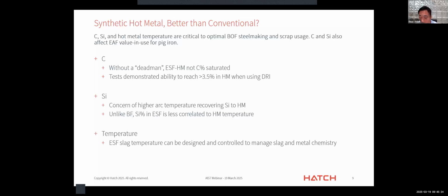And on the matter of silicon, the general conventional thinking is that a higher arc temperature will likely encourage the reduction of silica to recover more silicon in the hot metal. But based on our experience, unlike the blast furnace, the correlation between hot metal temperature and silicon in the hot metal is not as strong. And it is possible to very precisely control the silicon content in the hot metal through very precise feed and slag practice controlled engineering. Depending on the end user preference, it's possible to adjust it. For example, creating a higher silicon hot metal for BOF to use more scrap, or much less silicon to allow easier dephosphorization downstream. All of these are possible. And in general, by and large, the silicon content is comparable to blast furnace, but it's the much more consistent level of silicon that really provides the benefit.